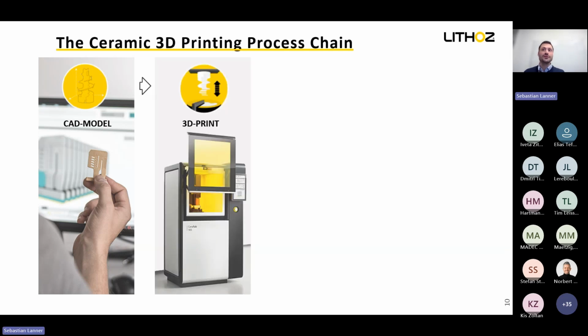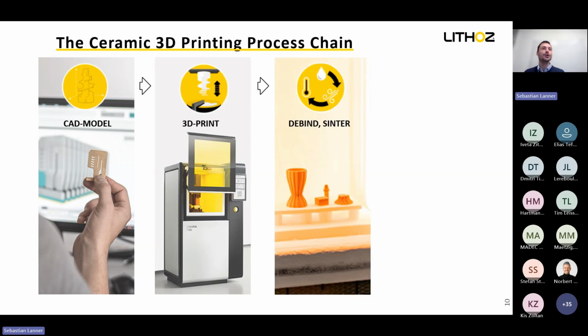The 3D printing process is very straightforward, and our system is built to run 24/7. So after the printing process and a small cleaning step, we will go into the debinding and sintering step. This is a very crucial step and has two steps. So we create in this debinding and sintering the outstanding final properties of the ceramic. I have in a later slide more details on what is happening here to create the ceramics.